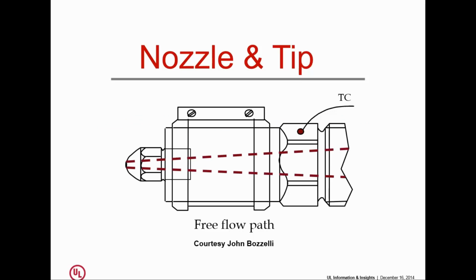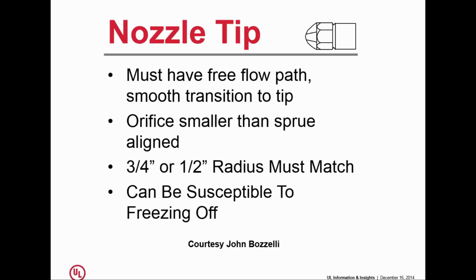The other thing we need is a nice streamlined flow path. So we're preventing pressure drops. And as we know, not sure why this ever happened, but history is history, we have two different radiuses out there for our mold, so we need two different radiuses for our nozzle tips. So you need to make sure if your mold has a 3/4 inch radius, so does your tip, and your 1/2 inch radius has the same radius as the mold.